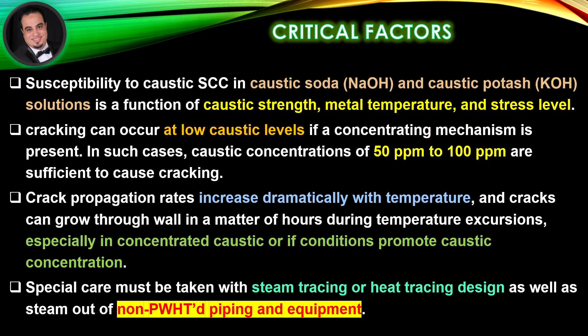Critical factors: Susceptibility to caustic stress corrosion cracking in caustic soda and caustic potash solutions is a function of caustic strength, metal temperature, and stress level. Cracking can occur at low caustic levels if a concentrating mechanism is present.